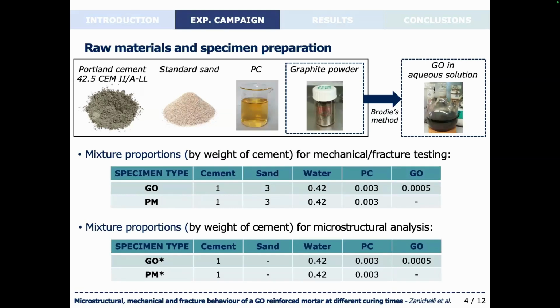Then we also cast the plain mortar specimens, that are the PM specimens, with the same proportions of cement, sand, water, and PC. And note that the proportions shown in the first table are those used to cast the specimens to be subjected to the mechanical and fracture tests, whereas the sand was not considered for casting the specimens for microstructural analysis. Both GO-reinforced specimens and plain mortar specimens were named GO-star and PM-star, since the presence of sand could make difficult the interpretation of the results from a mineralogical point of view.